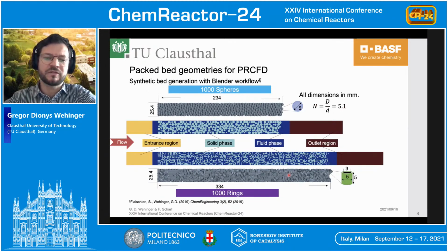On the other hand, we have 1,000 rings generated. Here is a packed bed, also with 5 millimeter diameter and height. But since the stacking is a little bit different, the length of this bed of rings is also a bit higher than the bed of spheres. But both of them are 1,000 particles included. Then in the next slides, the flow is typically from left to right. I included for the CFD simulations an entrance region and outlet region, just in order to minimize these effects on the transport phenomena inside the packed bed.